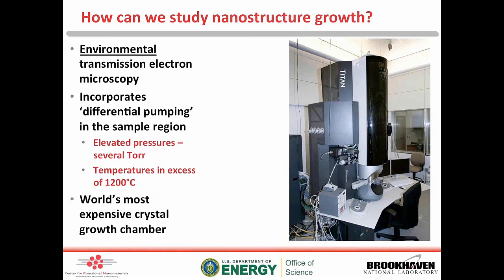This is the system we have this camera on at the moment. The idea behind this instrument is it incorporates differential pumping around the objective lens region. This is something that allows us to really go to very high pressures. We can go up to several torr during imaging, and with appropriate heating holders in excess of 1200 degrees C.